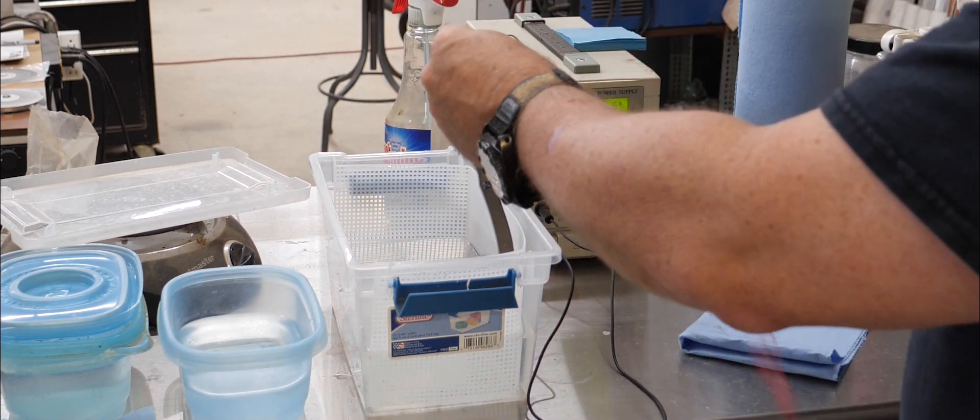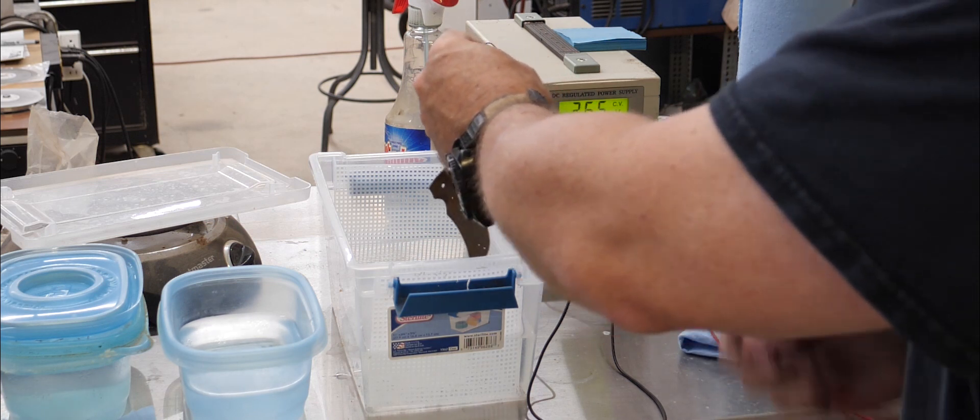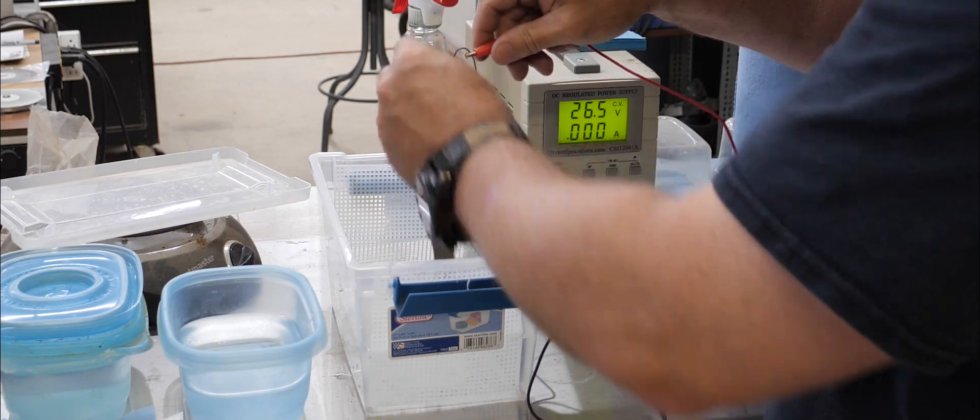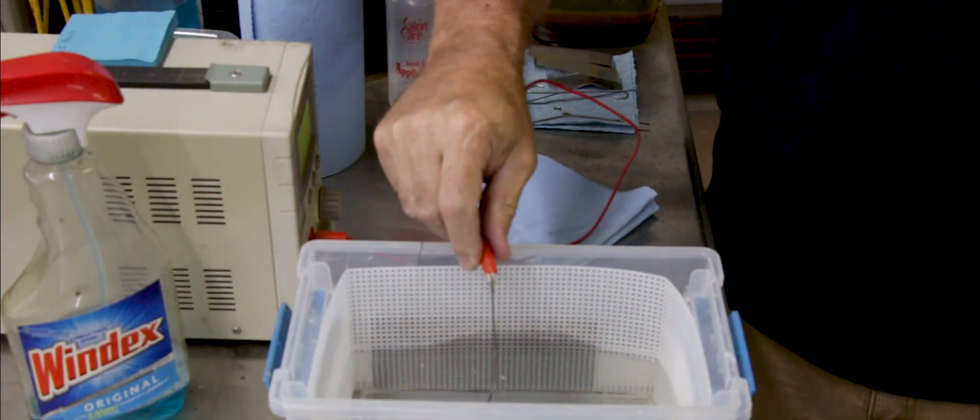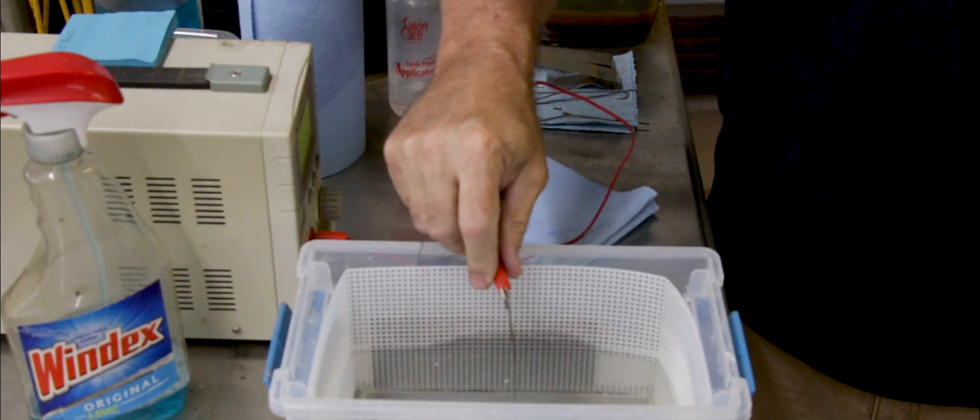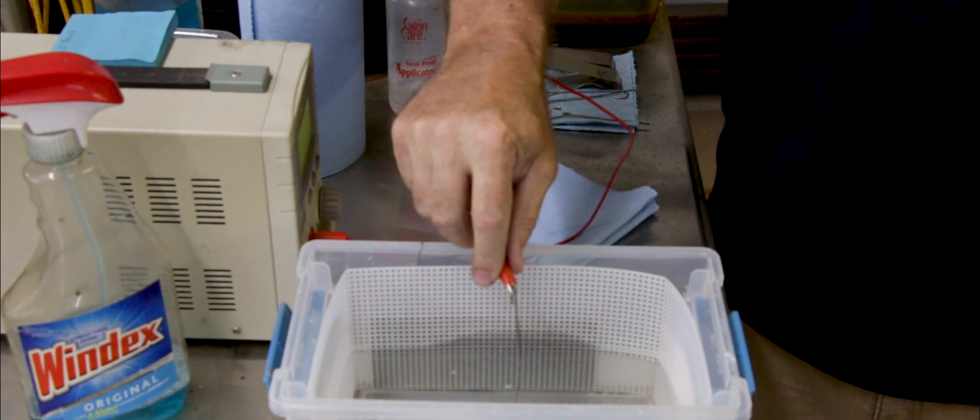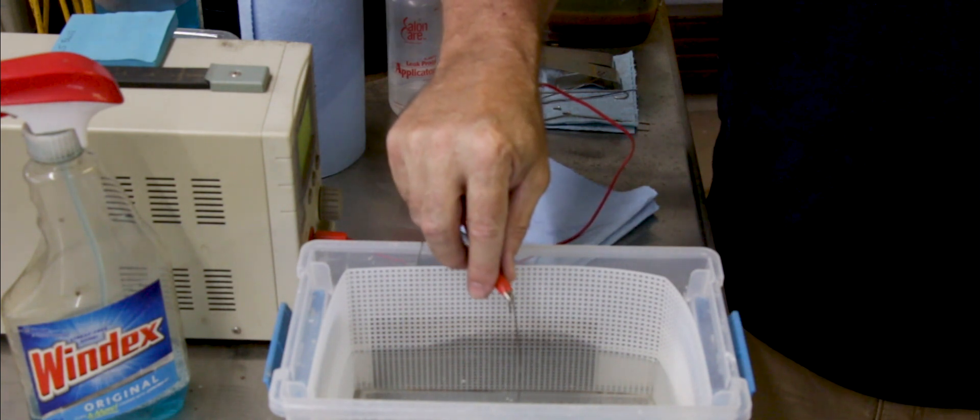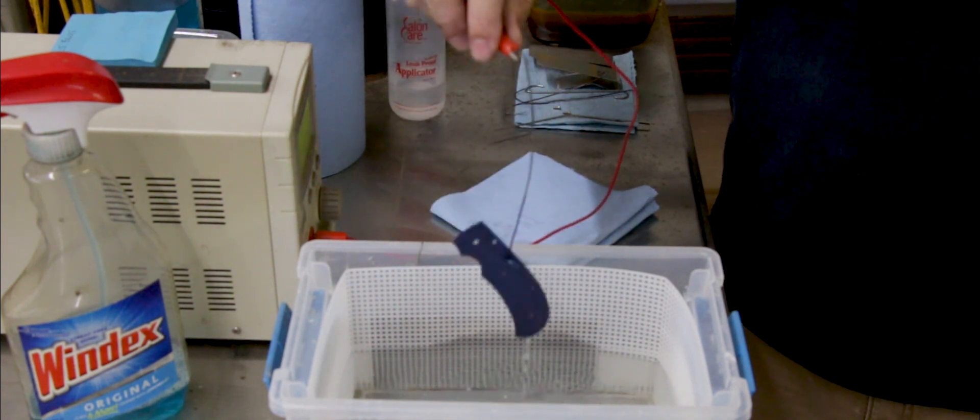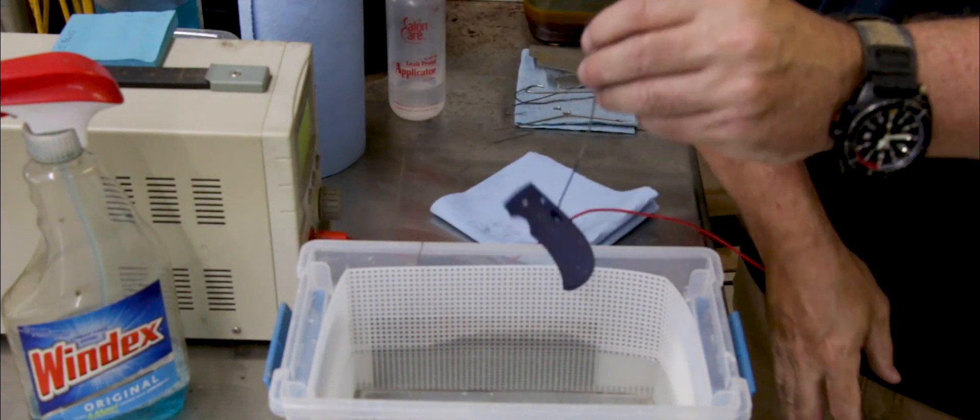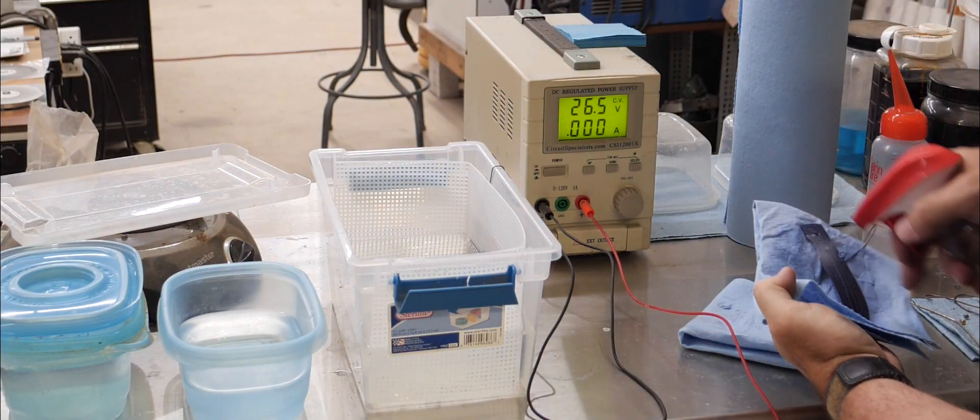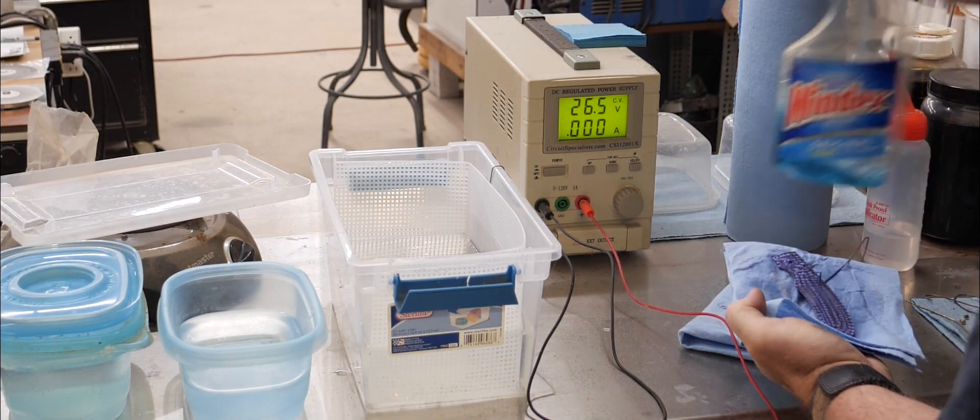I have found that the higher the voltage you go, the longer it needs to stay in the electrolyte. Part of this may be the fact that I only have a 1 amp power supply. I'm probably going to be upgrading soon to a 3 amp, but the 1 amp has served me well for years. And there's that nice blue. Do a little bit of cleanup and then it'll look like this.